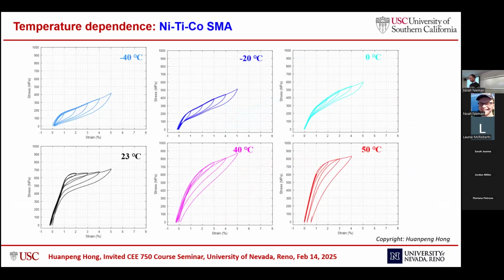So it also starts from room temperature. As the temperature increases, it behaves almost the same as the nickel titanium alloy. What is impressive is that when we lower the temperature to 0 Celsius, minus 20 Celsius, until minus 40 Celsius, this material still exhibits really good shape recovery capacity.